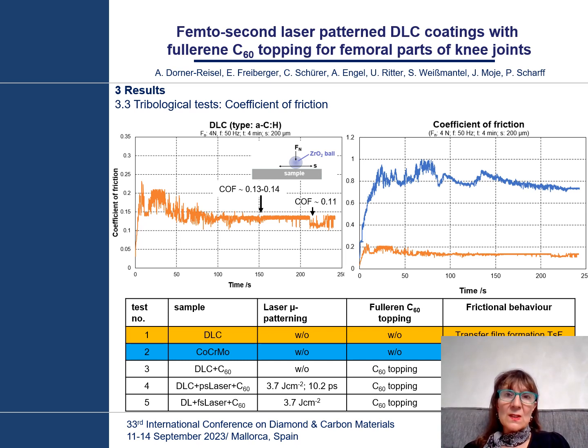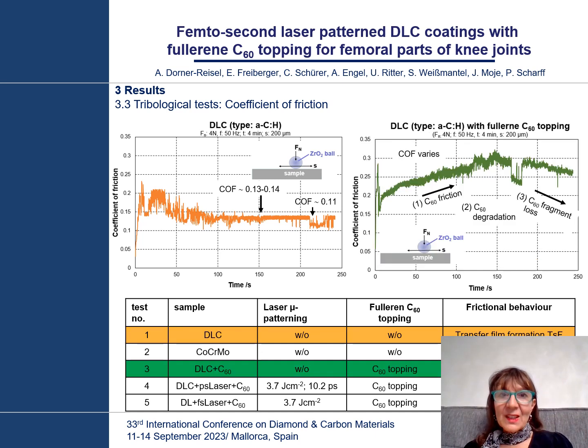If there is no DLC, there is solid-solid friction, and if there is DLC, we have a solid lubricating film that forms on top of it in the tribological loaded zone, a transfer film. That's why the coefficient of friction is reduced remarkably due to the deposition of the diamond-like carbon coating. Now, if we add additional C60 to the DLC coating, there is an increase of the coefficient of friction. C60 acts scratching.